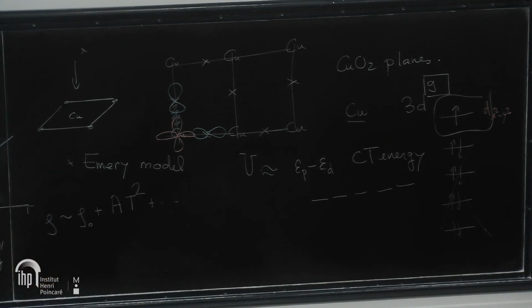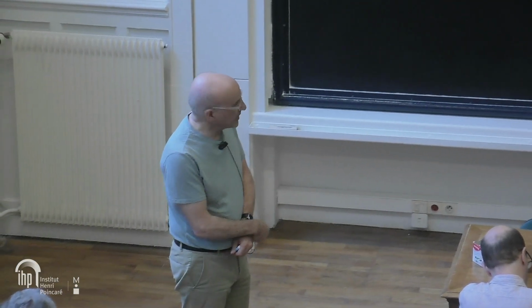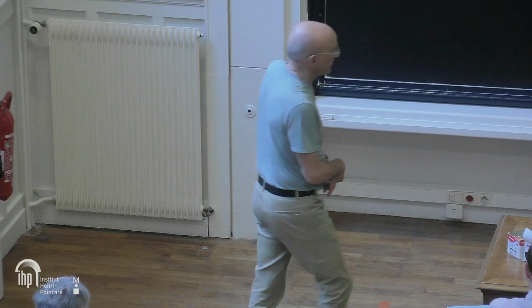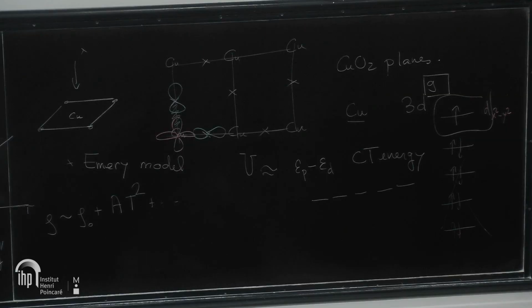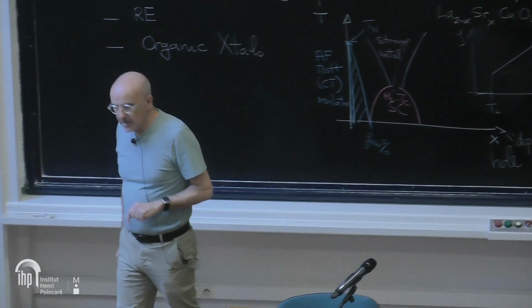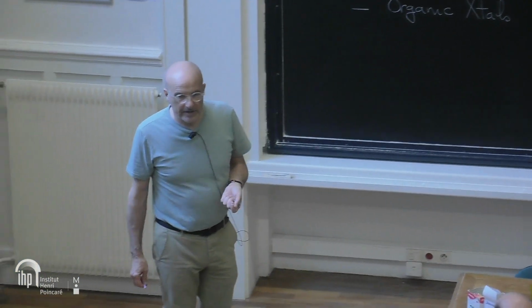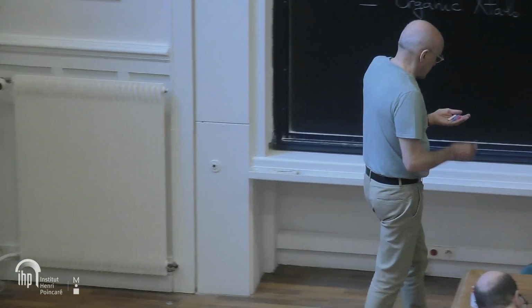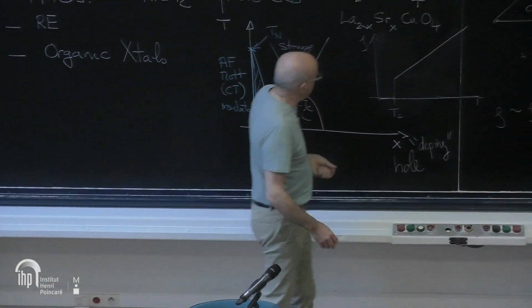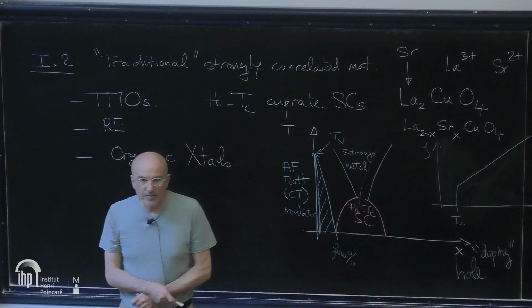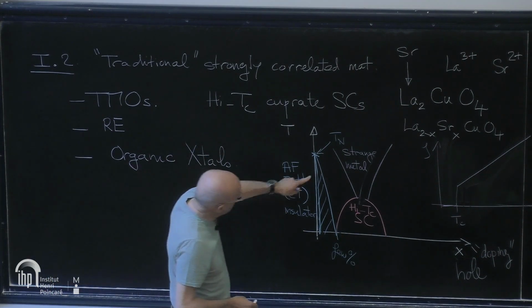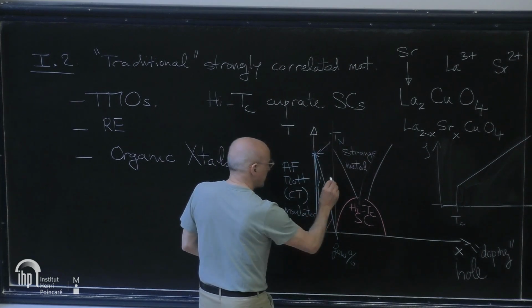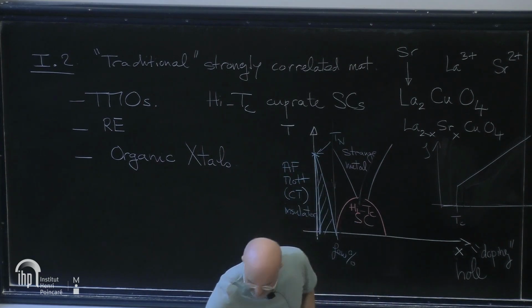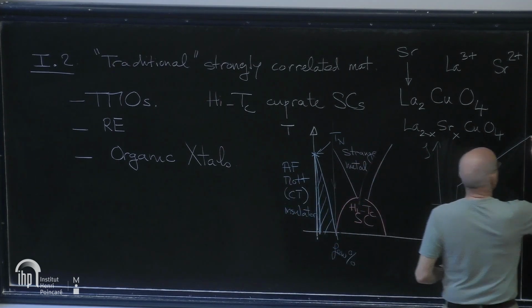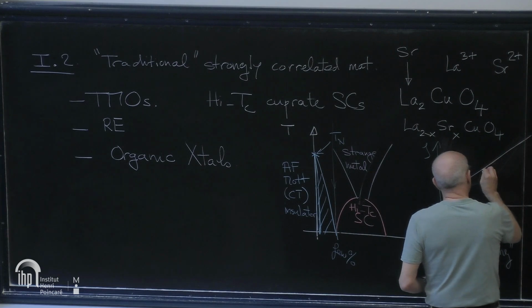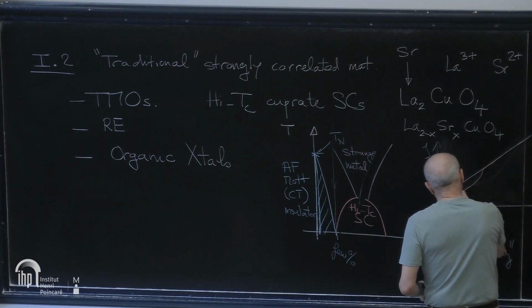This is an argument that was put forward by Landau and gave rise to the so-called Landau Fermi liquid theory. And so you see that the strange metal regime of the copper oxide superconductor is a challenge to Landau Fermi liquid theory. Now, this behavior of perfect linearity does not persist down to arbitrarily low doping. If you actually measure resistivity in this regime coming down that way, what you will find is that at high temperature, the resistivity is still linear, but then before it reaches Tc, it does something like that.